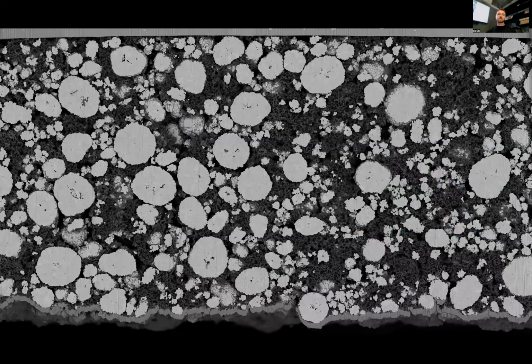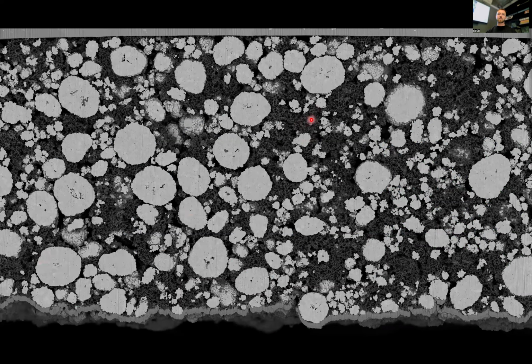So here is an image of a lithium-ion battery cathode material. The image is about 100 microns thick. The electrodes are about 100 microns thick, and the particles inside them are roughly 10 microns thick. Obviously, many of them are much smaller than that. In between the particles of active material, you also have sort of fuzzy carbon binder domains. That's a mixture of a polymer that holds everything together and some carbon black that facilitates electronic transport.